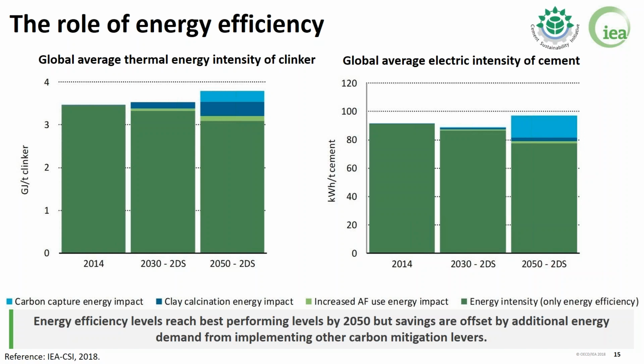And also, for instance, a strategy that is being looked at, which will be further explained later on, is to support the reduction of the clinker to cement ratio by integrating further calcined clay within the cement composition through blended cements. And this, of course, also has a thermal penalty that has been taken into account, as you can see here, as well as an electricity penalty.